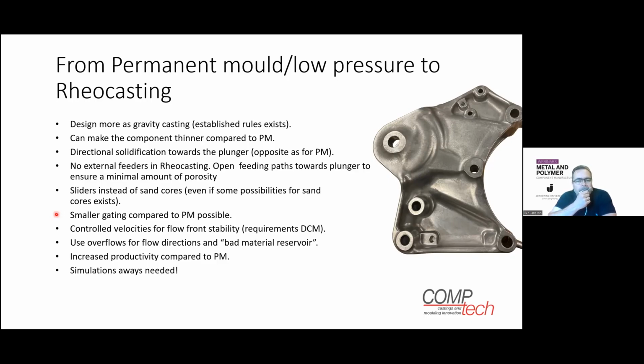Here it's important that we have a controlled velocity for flow front stability, because in these types of castings we see a very laminar filling behavior, totally opposite from high pressure die casting, I would say. Overflows are somehow very important in these types of castings, where we need to make sure that we get out the bad material, let's say, or the first material, flow fronts and things like that. We see here also that we have an increased productivity compared to permanent mold, and basically we are introducing a totally new palette of business possible for high pressure die casting compared to what they can do today. And also here, I would say simulation is always needed.